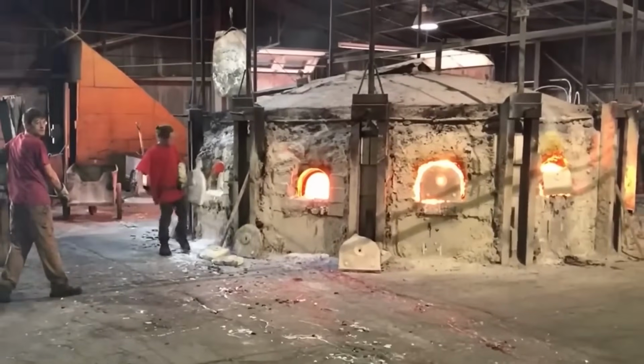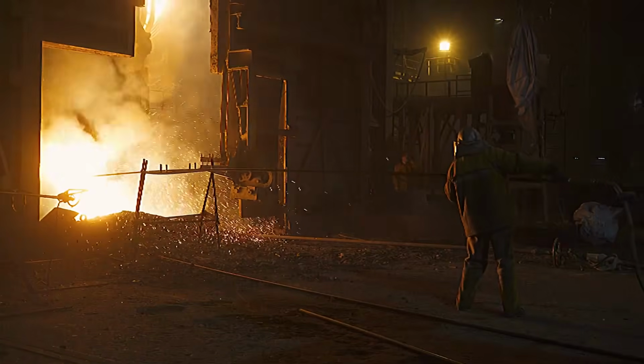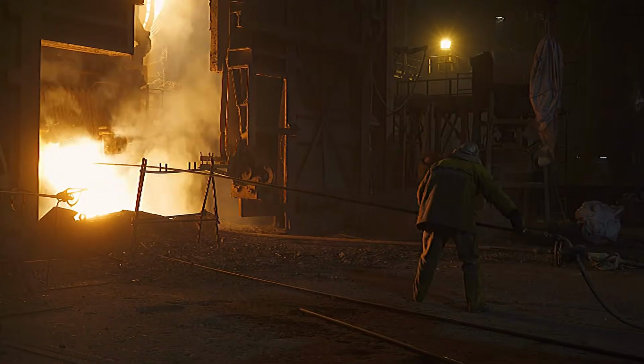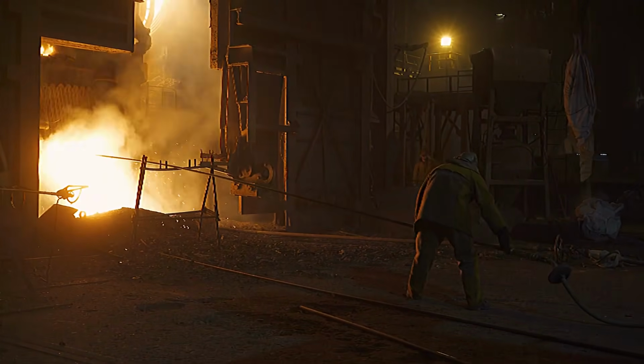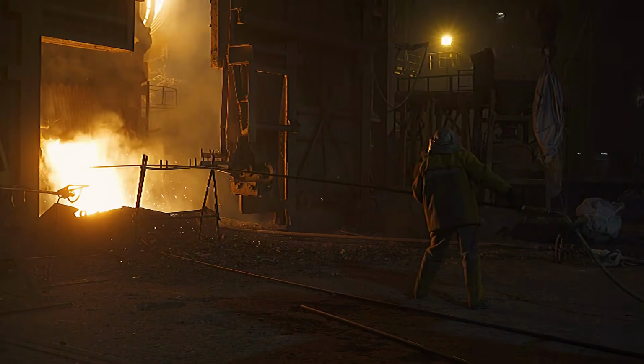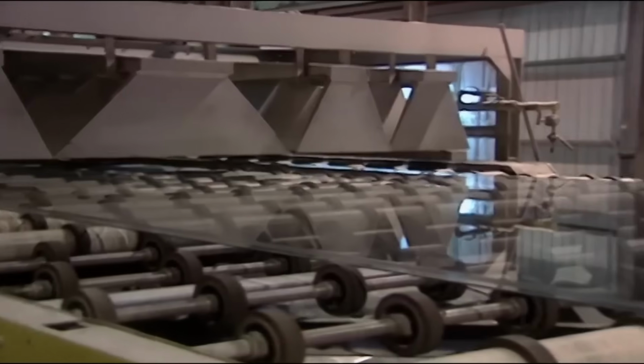Above that rate, the outer surface of the sheet cools faster than the interior, freezing a permanent stress gradient into the glass. The result is a sheet that may pass visual inspection, but fractures unpredictably under load. Below the strain point, the glass can be cooled as quickly as the equipment allows. Faster cooling below 511 degrees does not reintroduce stress because the molecular structure is already immobilized.